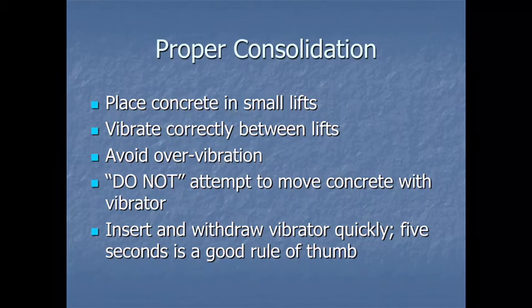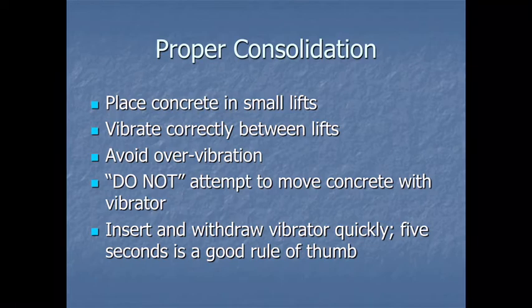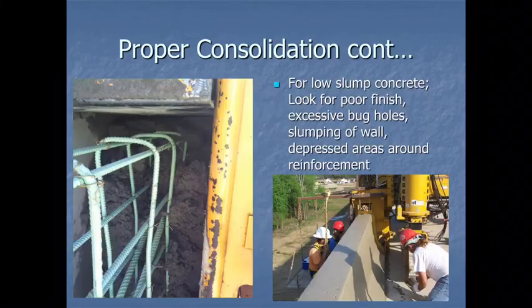Insert and withdraw the vibrator quickly — five seconds is perfect, anywhere from three to five. Going in and out too fast won't give enough vibration. Keeping it in longer than five seconds will cause over-vibration.